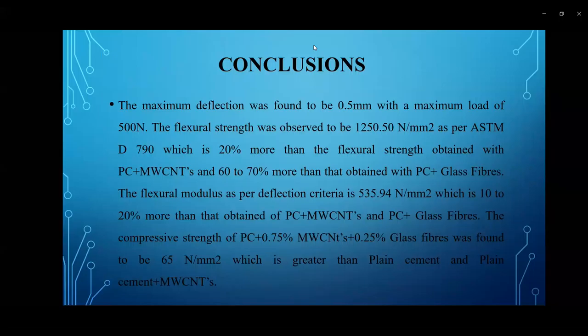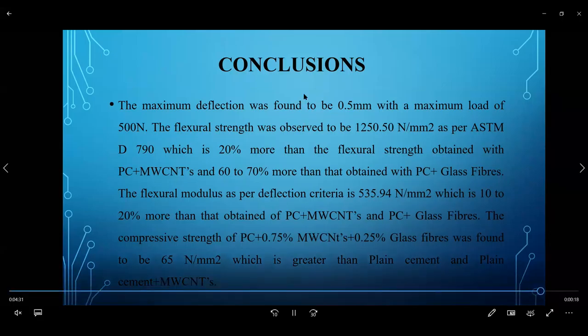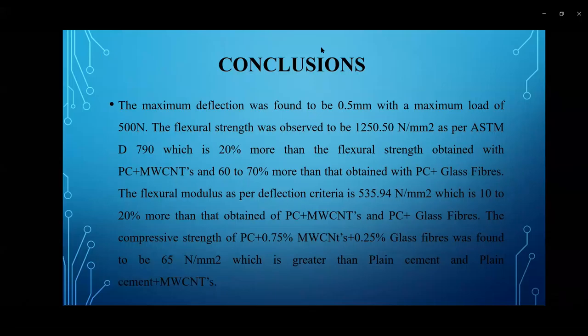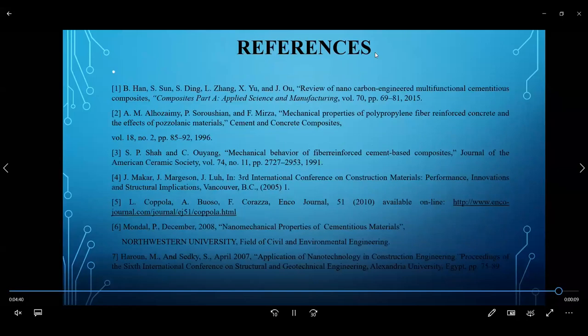And the flexural modulus as per deflection criteria is 535.94 Newton per millimeter square, which is 10 to 20% more than that obtained of PC plus MWCNTs and PC plus glass fibers. The compressive strength of PC plus 0.75% MWCNTs plus 0.25% glass fibers was found to be 65 Newton per millimeter square, which is greater than the plain cement and plain cement plus MWCNTs.